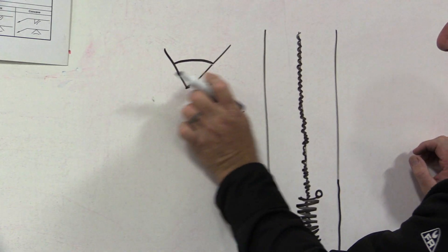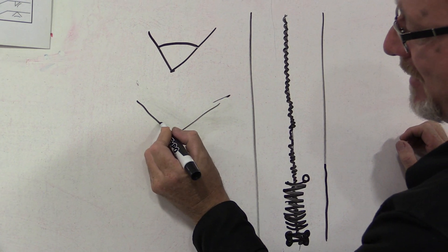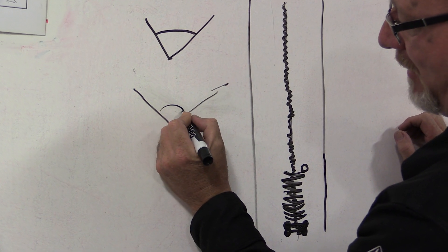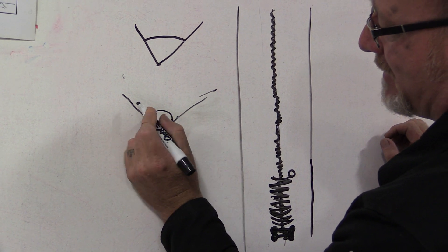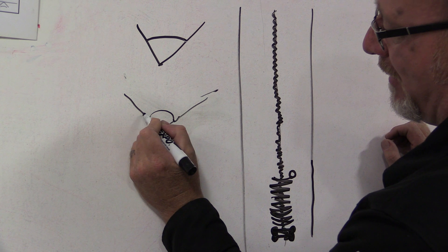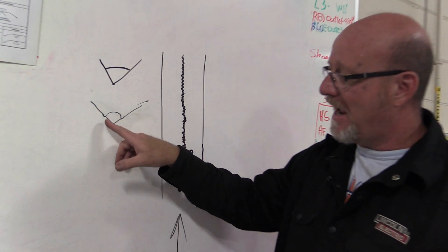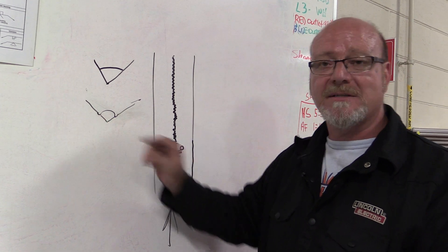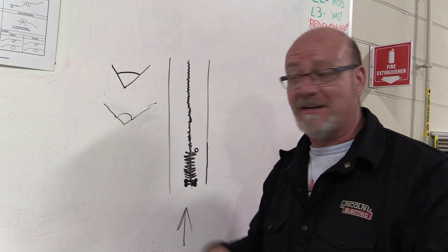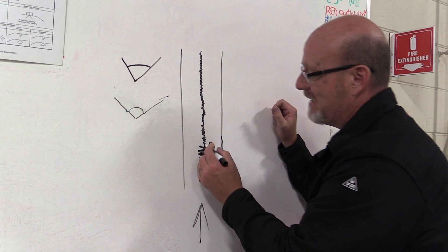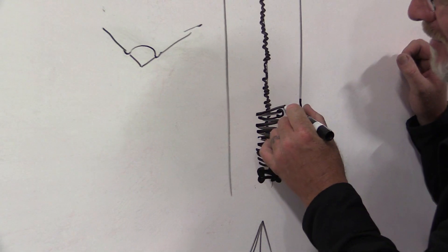When we pause on the sides, that allows this weld to fill up. If we don't pause on the sides then we get two things. We get the weld bead that's humped up in the middle, but we also get a bigger problem and that is undercut on the edges of the weld. An undercut is a serious discontinuity in the weld and can turn easily into a defect to make the weld rejectable.